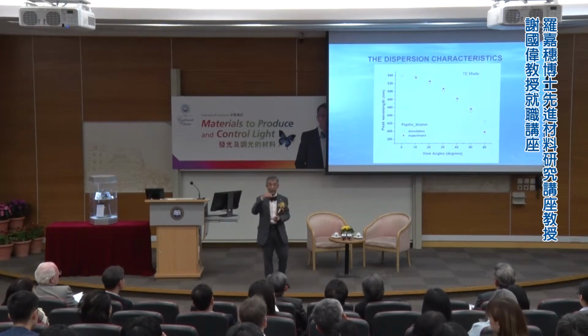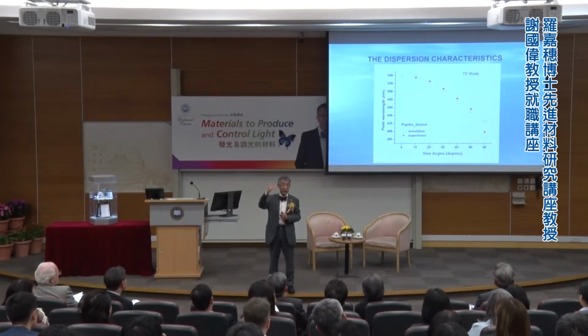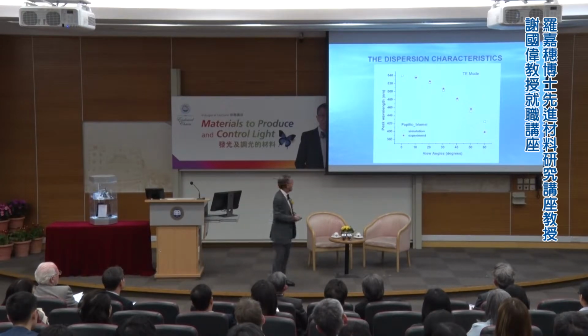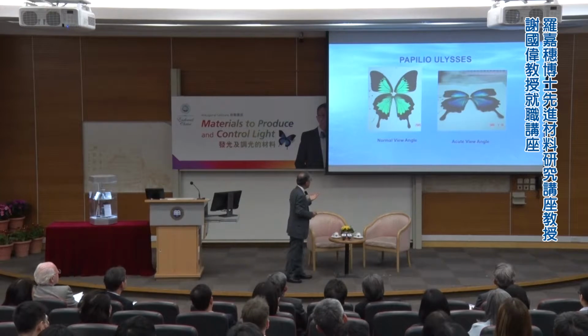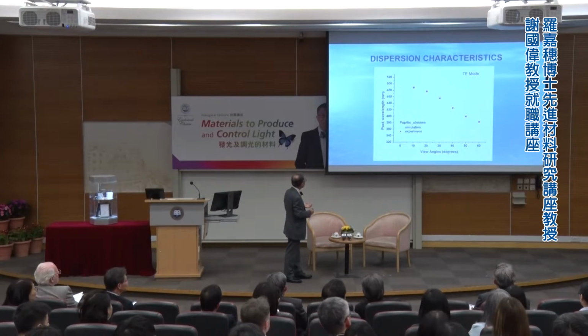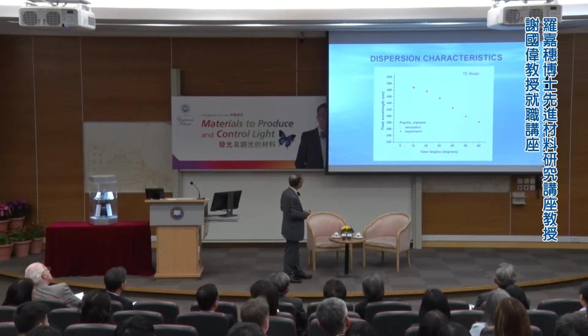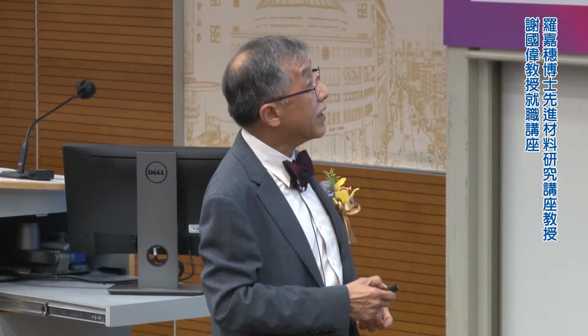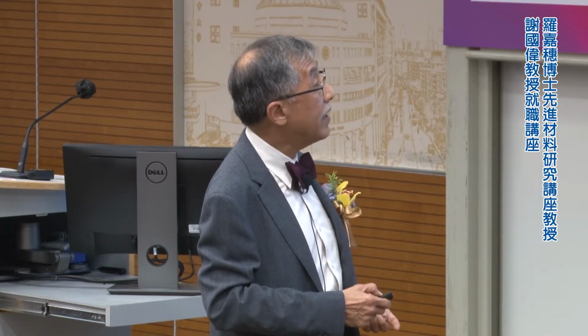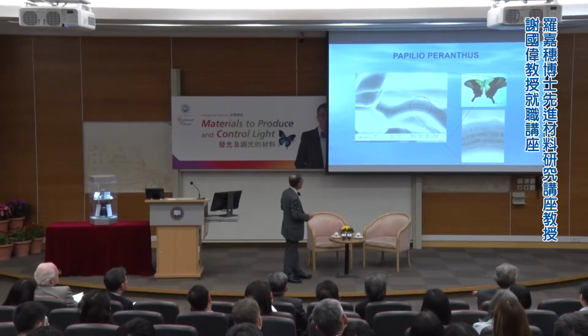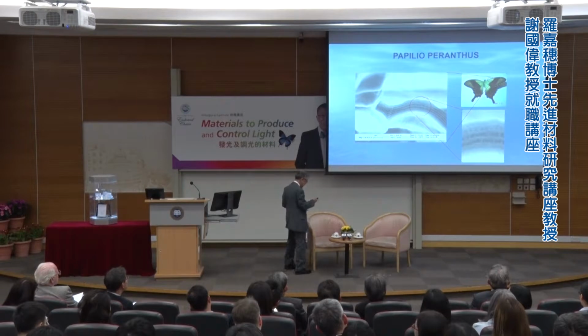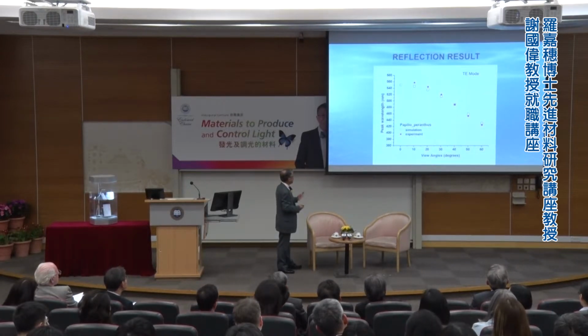Then we know the layers, how many layers, and what effects they have. We can simulate that. And we do the same thing for Ulysses. Again, we can see that we use that to give you different changes in color as you look at different angles. And Peranthus, again, you can see the layers here. This structure is looking actually quite good, much better than the Blume one. And again, we plot that.